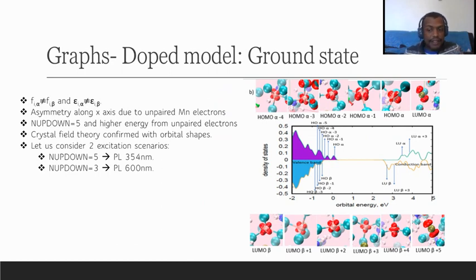And if that does happen, it's going to be at LUMO beta, and then the difference between LUMO beta and HOMO alpha would be around 2.5 or something like that, and that would confirm a redshift of the photoluminescence wavelength, which would be around 600 nanometers, and that was shown in the experimental graph that I showed in the introduction. Next slide, please.